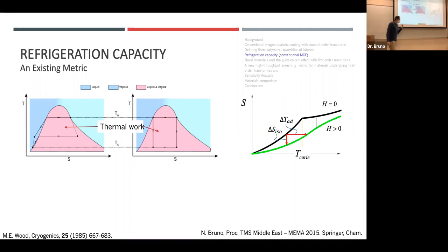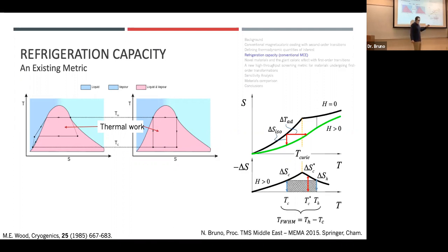Wood and Potter in the 1980s developed a metric with this Carnot cycle, right? And they called it the refrigeration capacity. So they said, okay, in literature, we have these ferromagnetic materials that we apply magnetic field to. We have a change in entropy, and we have that as a function of temperature. So here I plot delta S, their entropy change as a function of temperature, which is the difference between these two curves. And the cusp here is the ferromagnetic Curie point of our material.